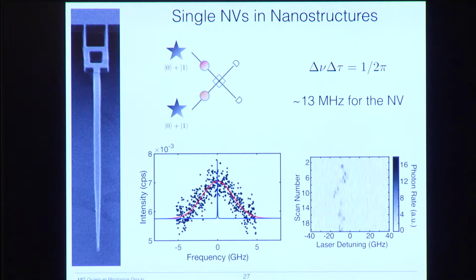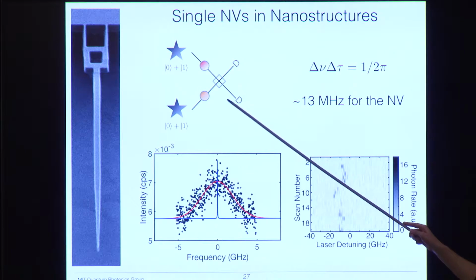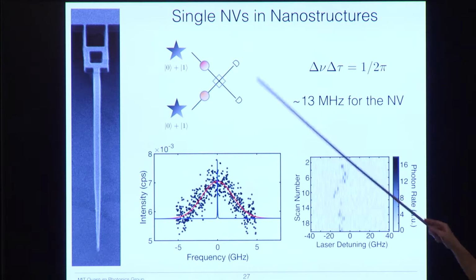Unfortunately, if we measure an NV, this is what it does look like. If we take many measurements at each frequency, and build up statistics at each frequency, we see a very broad line, or if we just do quick scans over the resonance, we see that it hops around a lot in time. And so this would not be good for quantum information processing, because you can see that every successive entanglement attempt, there'd be a slightly different frequency, and so when we measure one photon, we can tell which NV center it came from, because the two NV centers will have slightly different frequencies, and so we don't get high fidelity entanglement.